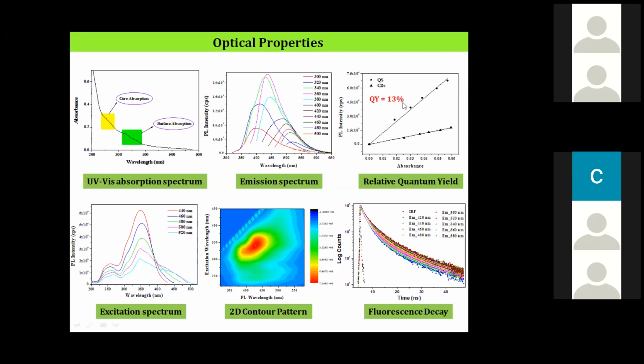So quantum efficiency also we measure it - it's around 13% quantum efficiency. Now, one can extensively use 2D contour analysis to find out the composition or analysis of how many components are present in this. And then fluorescence lifetime analysis - one can measure the fluorescence lifetime at different wavelengths and find out it's never a single exponential. You always see that they're all multi-exponential because of the presence of multiple components in solution. So this is how you can look at the photophysical properties of all this material.